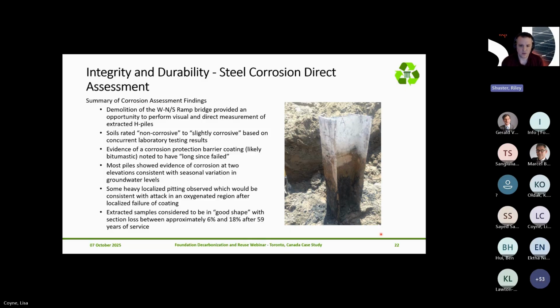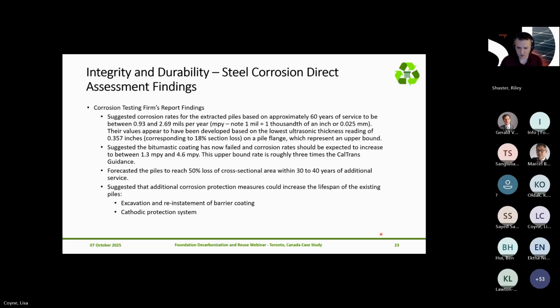The majority of piles showed evidence of corrosion at 2 different elevations, which would be consistent with seasonal variation in groundwater. As the groundwater fluctuates, the most active area of corrosion is going to shift in and around that groundwater level. And there was also some evidence of pitting corrosion, which would be consistent with areas where the coating may have failed first and you had the steel exposed. Overall, the extracted samples were described as being in generally good shape, and the maximum section loss reading, individual reading that was measured was 18% after 59 years of service. Next slide, please.